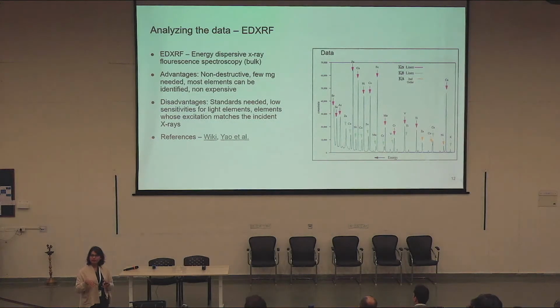And then you add the third element, and then you do the EDXRF again, and you see what is the count of each element that you get. And whatever the relative changes in the peaks are tells you the composition of each element. So these are the kind of references you have in the EDXRF experiments. And this doesn't really work well with light elements. So these are typically done for heavy metals, like you would see in this particular graph.